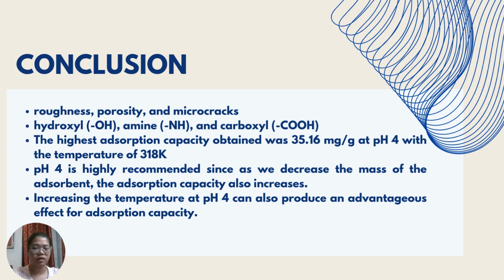Scanning electron microscopy, or SEM, analysis revealed notable changes in surface morphology, including increased roughness, porosity, and microcracks, which contributed to enhanced adsorption performance. Fourier transform infrared spectroscopy, or FTIR, confirmed the presence of key functional groups, specifically hydroxyl, amine, and carboxyl, which facilitated strong interactions between the ibuprofen molecules and the adsorbent surface. pH 4 is highly recommended since as we decrease the mass of the adsorbent, the adsorption capacity also increases. Increasing the temperature at pH 4 can also produce an advantageous effect for adsorption capacity.